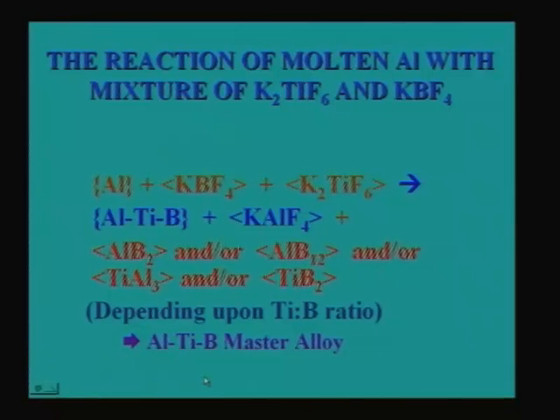Only thing is, in an aluminum titanium boron grain refiner, we do not really bother whether you are getting only TiB2 or only Al3Ti or a combination of these two, because both Al3Ti and TiB2 can act as nucleating sites for aluminum during solidification. So even if you have a mixture of Al3Ti and TiB2 in a grain refiner, it is okay as a grain refiner, but it is not really okay as a composite, because as a composite Al3Ti is more brittle. So people do not want to have Al3Ti in an aluminum TiB2 composite. So one has to control that.